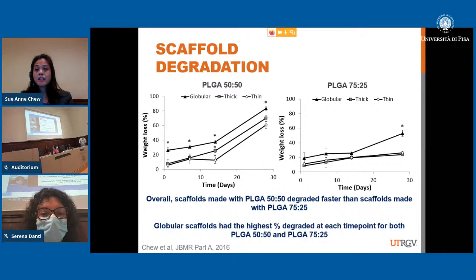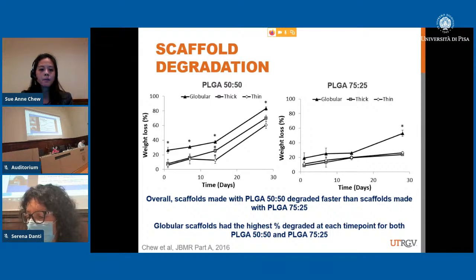So the next thing was scaffold degradation. We wanted to see how these different architectures could lead to different degradation rates. We were expecting that the thin one would degrade faster. We were thinking, okay, this SVR was the highest. This means that more water molecules can get to the ester bonds on the PLGA and degrade it. But the thing is, we saw the opposite, right?